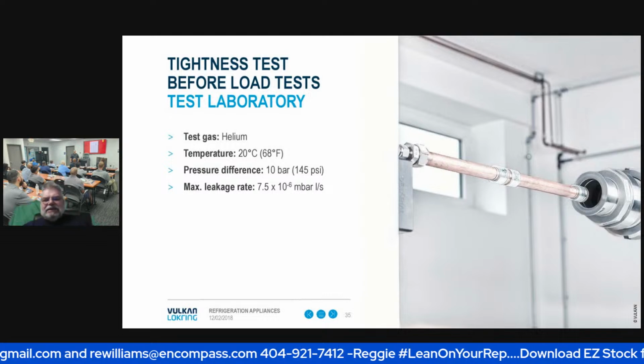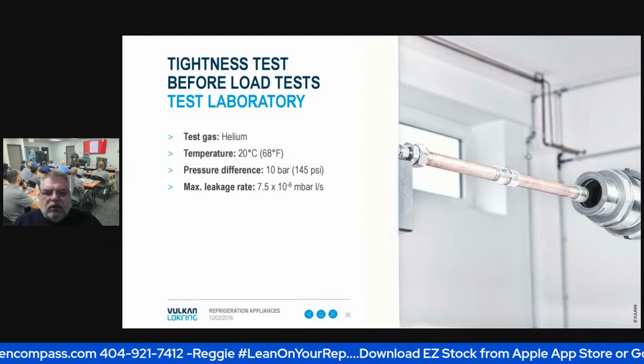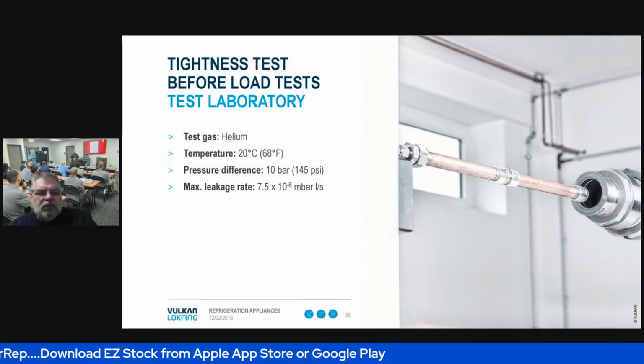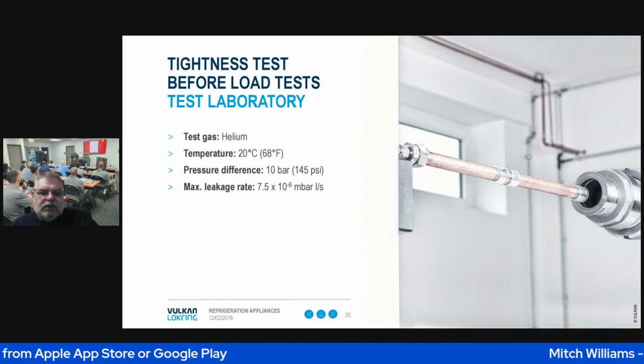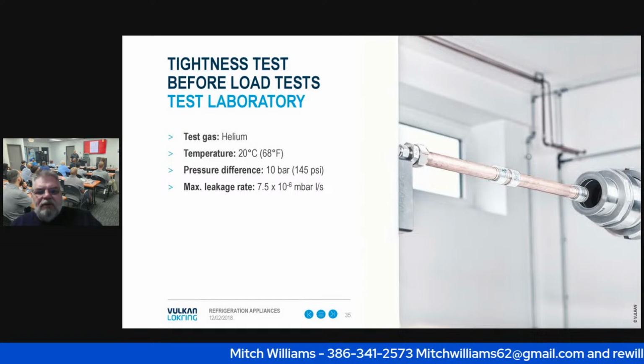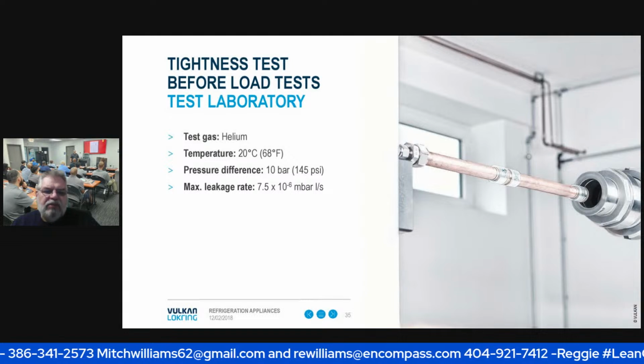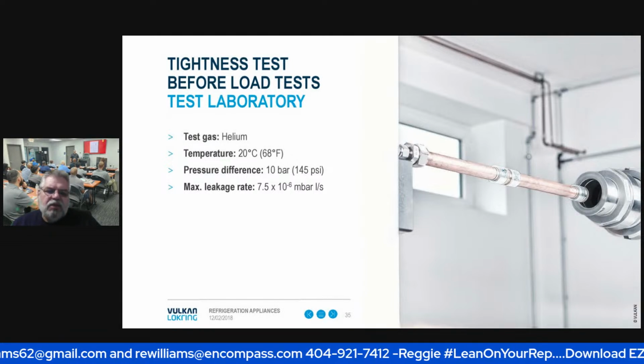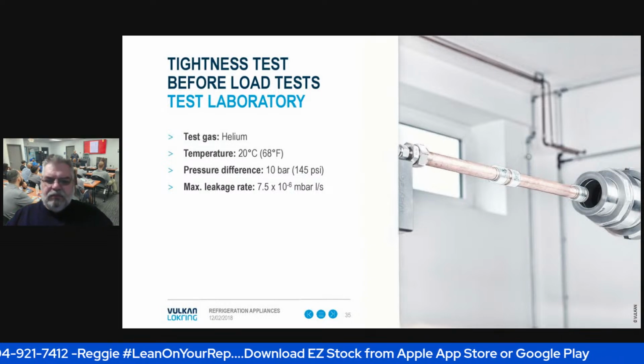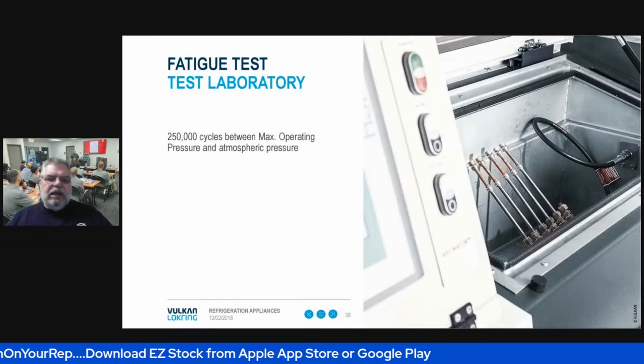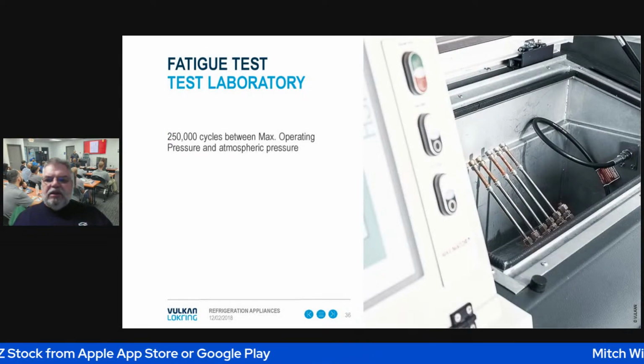Okay, so for the tightness test, that's the first test that they do. They inject helium gas into it. The temperature is at 68 degrees Fahrenheit. The pressure difference is 145 psi. The maximum leakage that is allowed is 7.5 times 10 to the minus 6 millibar. Okay, that is super tight. Of course, it's got to be, because we can't have a leak in the system.